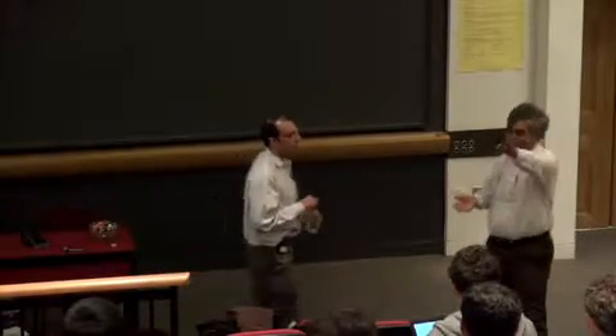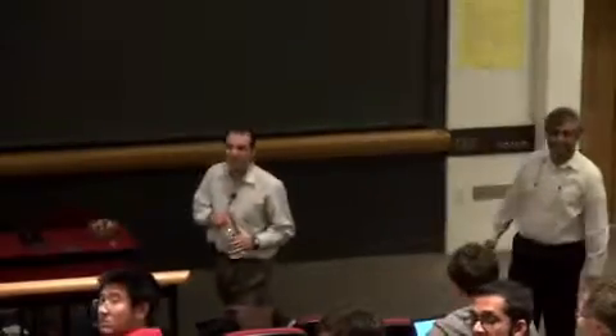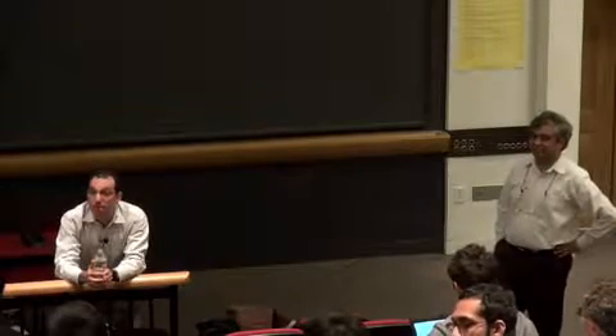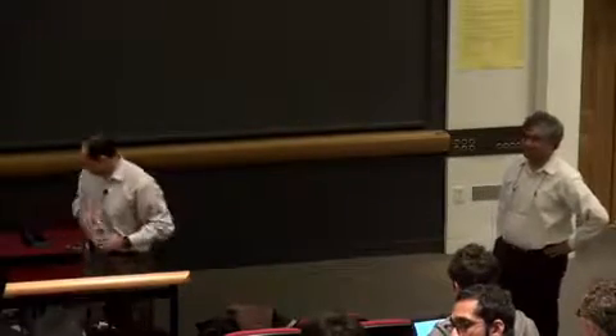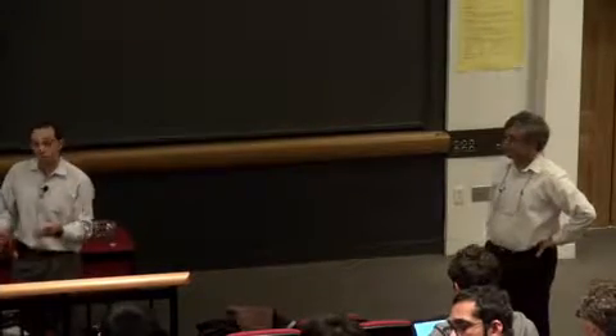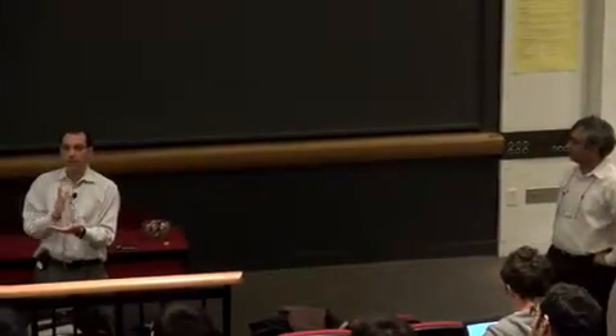That's fine. Okay, sorry. So let me ask that question. Somebody said that in the real world there is experiment, so the model is irrelevant. Yes. Okay, so what we do know is that surface anisotropy typically tends to favor some direction of the spin. For example, if you put iron on copper, you find two spin states depending on where the iron sits. If it sits in the middle, it likes to point up because that's symmetric. If it sits on a bridge site, it will point one way or the other.